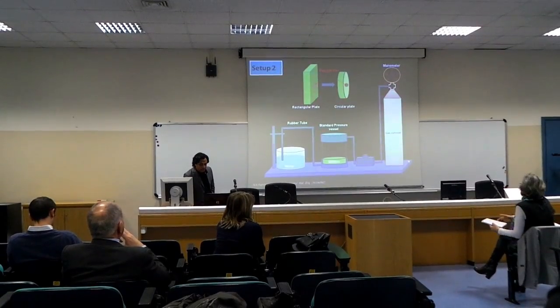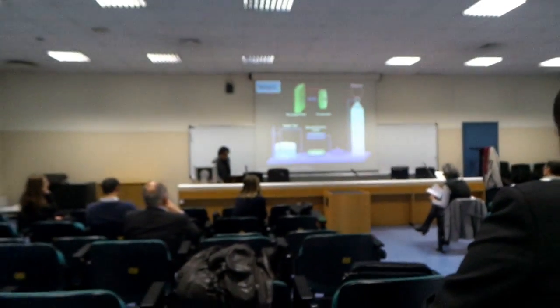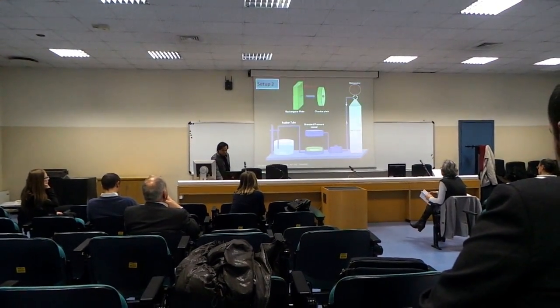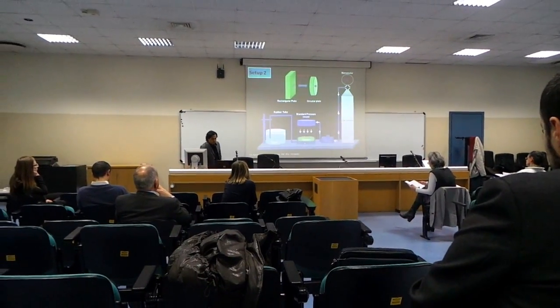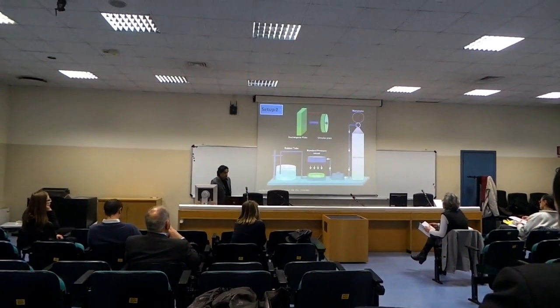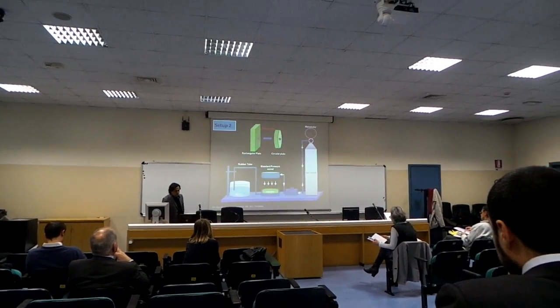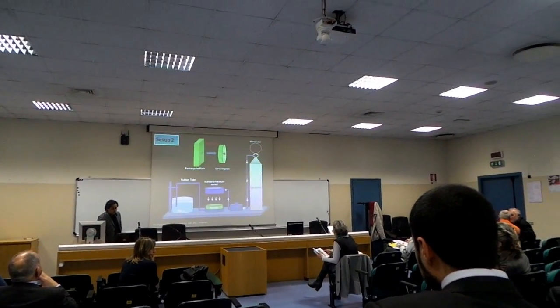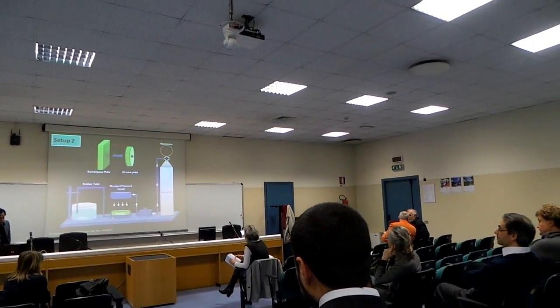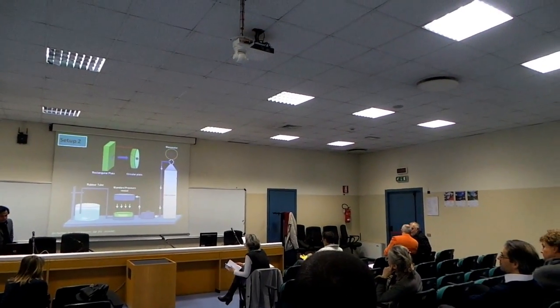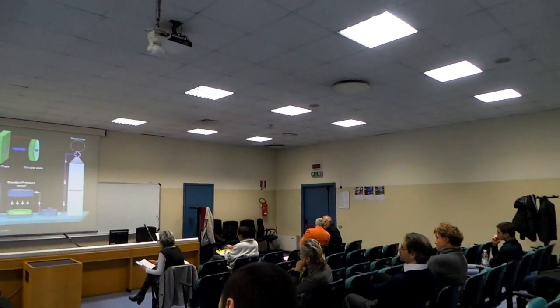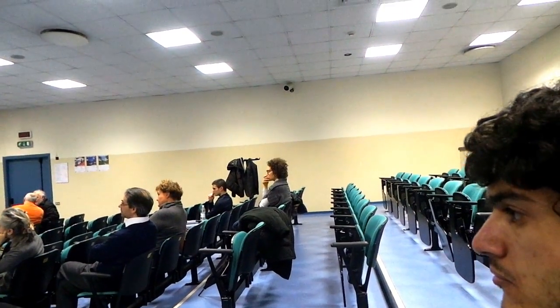And then the sample here was exposed to a pressure difference for a certain period of time. If the damaged zone is not completely closed, I would see a water bubble immediately in the water beaker. But if it does not show the evidence of a water bubble in the beaker, it means the sample is self-healed. So these two setups were very important to identify the healing ability and healing efficiency in each sample. Now I'd like to go through some important results in each system.